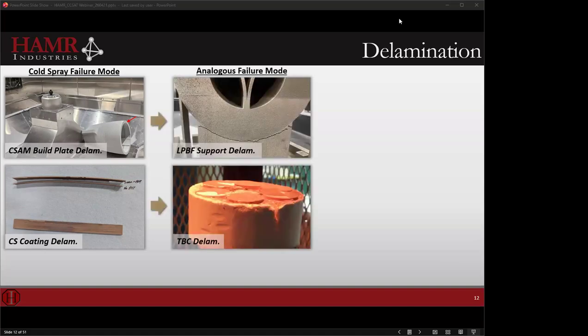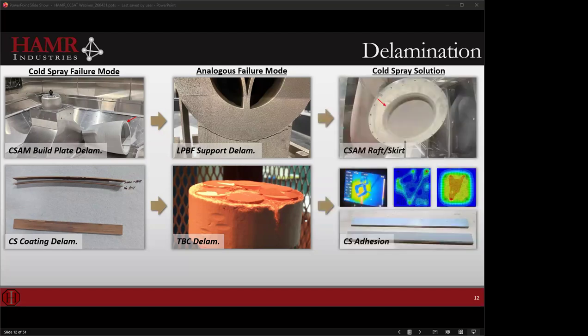Fortunately, for this, we can borrow from what's been done in the literature. There are analogous failure modes. In additive, there's support failure, there's failure from the build plate, and there are a lot of solutions that have been simulated, modeled, and designed. Likewise, coating delamination is a chief concern in the thermal spray world. If we look at thermal barrier coatings, the primary function is how do you avoid delamination in a system that is prone to delamination. So a lot of these challenges have been worked on previous to cold spray.